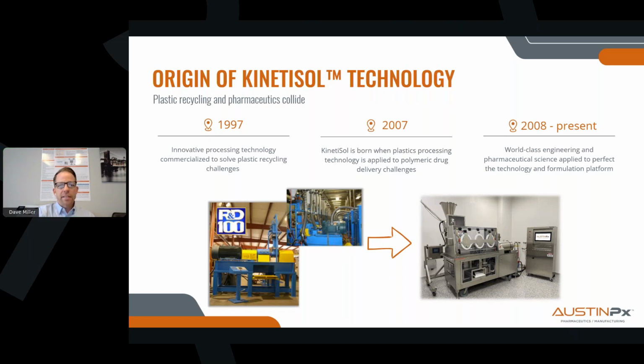The technology began life in 1997 as a plastics recycling innovation, which was an elegant engineering solution for dispersing incompatible polymers. A decade later, that same principle was applied to pharmaceutical formulation challenges. And since 2008, we've refined KinetiSol into a fully commercialized platform with world-class engineering and pharmaceutical science behind it. The idea is simple but powerful. We harness frictional and shear energies to instantly mix, melt, and disperse the API in the polymer without the use of solvents or external heat. And what results is a molecularly uniform amorphous dispersion that's produced in seconds as opposed to minutes, and without the use of solvent or applied heat, as I mentioned.